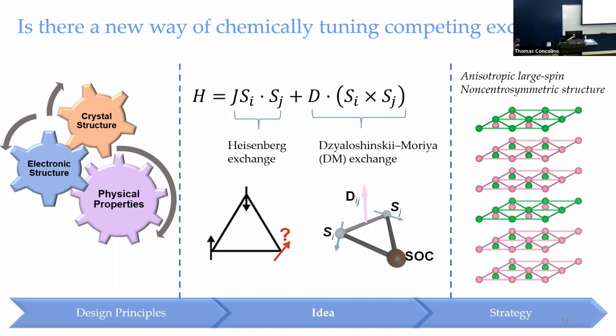And what would we get? Because in order to induce the DM exchange interaction, we will need a system that lacks inversion center symmetry and has significantly large spin-orbit coupling. So we need broken inversion center symmetry, right? And also coupled with the triangular frustrated lattice. So, also inspired by Martin's work, we look into anisotropic large spin, and then we add a noncentrosymmetric structure. So let's say we have a triangular layer stacking along c, but if you look at this one, there's actually no inversion center symmetry, right? That this structure can accommodate. So then what will we get out of that?